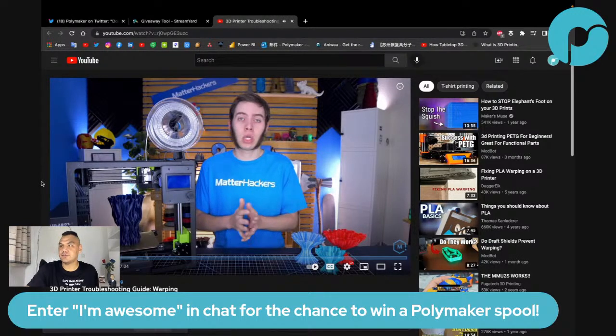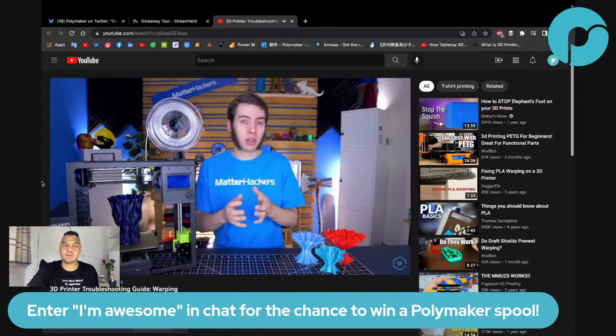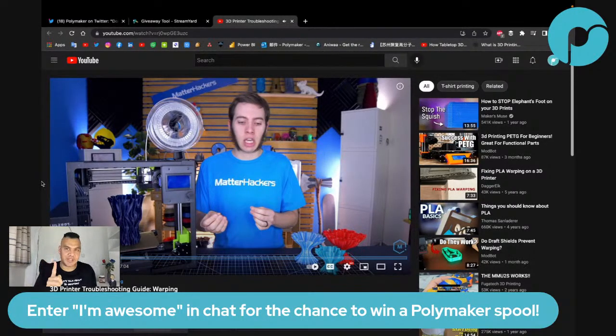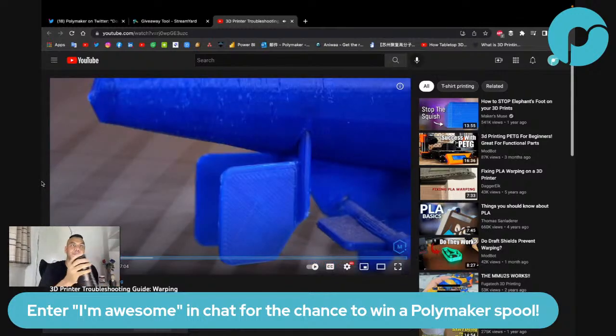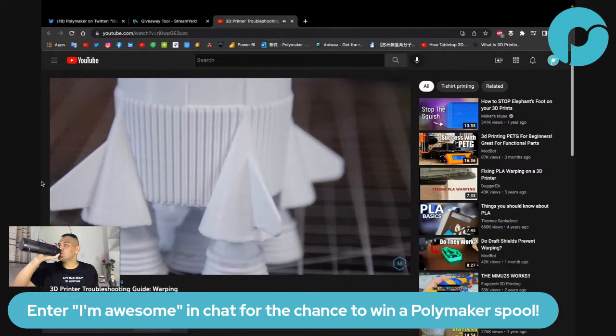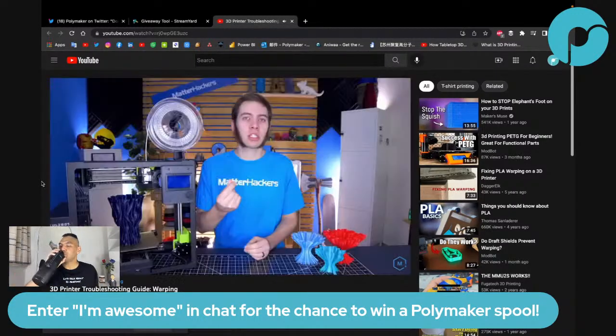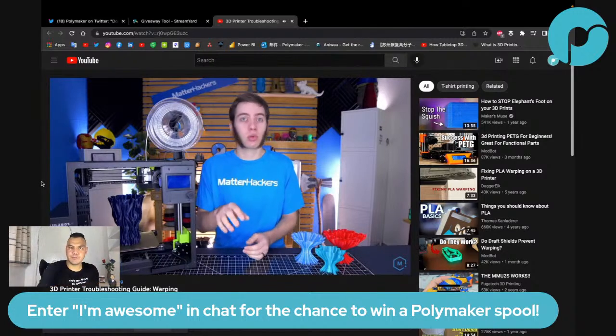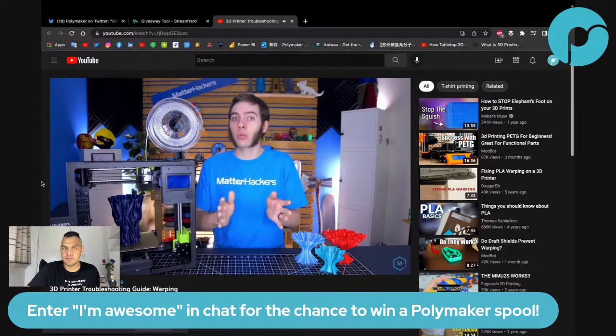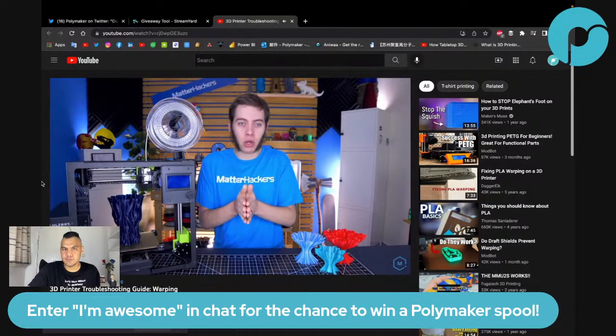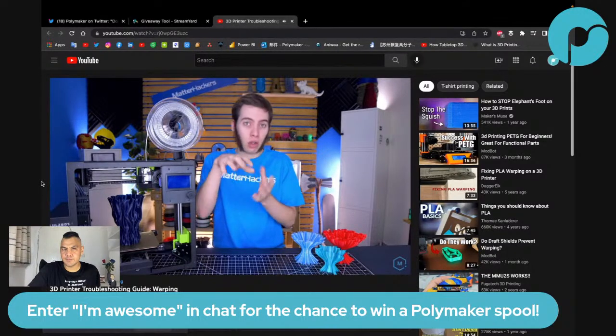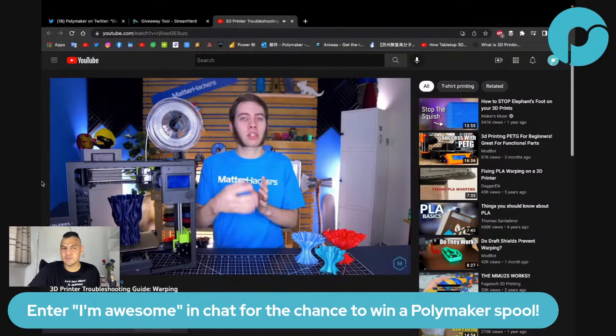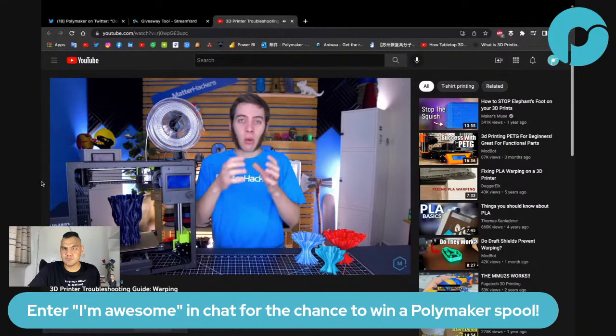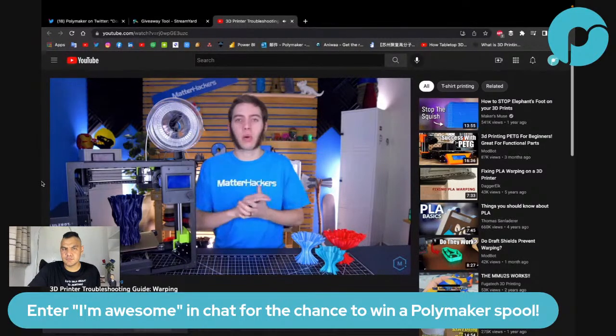Really calibrated, or even you just have a model that's just really thin. So if you're printing something like a shark fin or like the fin of a rocket, that could have a really thin base, and just because of how much heat is being put into it from the nozzle. So even if you're printing PLA, which is normally not warpy, if you're printing it in a very small thin part, the heat of the part on it that's just keeping it warm constantly and is just adding more heat into it can just cause it to peel away.